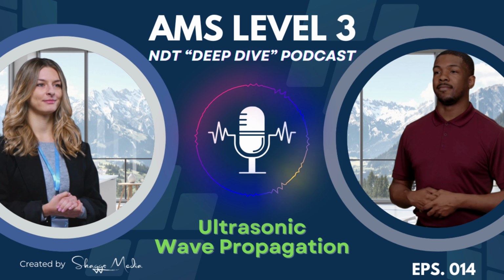They're always slower than the bulk transverse wave, right? Always slower, yes. And that has a practical use too, because higher frequency Rayleigh waves are confined even closer to the surface due to attenuation effects. You can actually tune the frequency of your probe to investigate different shallow depths. Very handy for finding surface-breaking cracks.